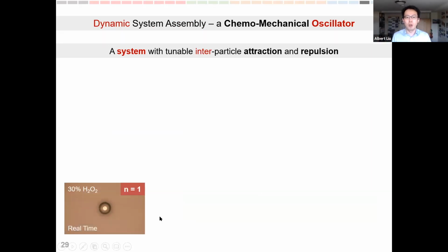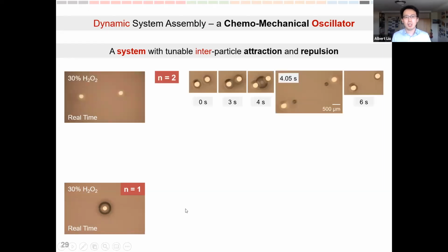I'm going to play this real-time video of one single particle as I go through this slide. But note what happens if I put two exactly same particles together at this air-water interface. The bubbles get attracted to each other through the Cheerios interaction we talked about before. And as the bubbles get closer to each other, they will merge into a single bubble in the middle, because by merging into a single bubble, it decreases surface area and hence surface energy. As the bubble collapses into one bigger bubble in the middle, now the platinum patches can see more hydrogen peroxide again. So it continuously generates the oxygen that fills into the central bubble, and eventually the bubble pops. And this bursting of the bubble will eject the two particles away from each other, forming this mechanical oscillator.